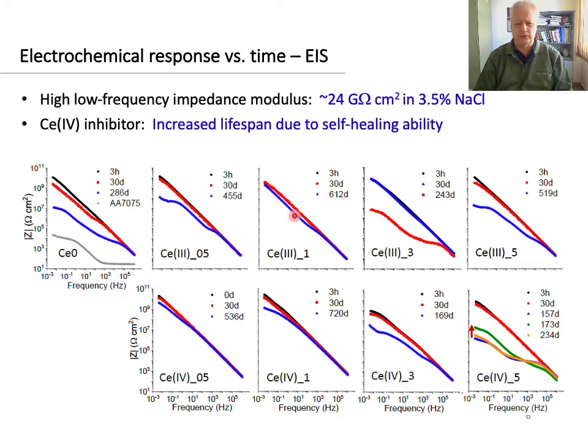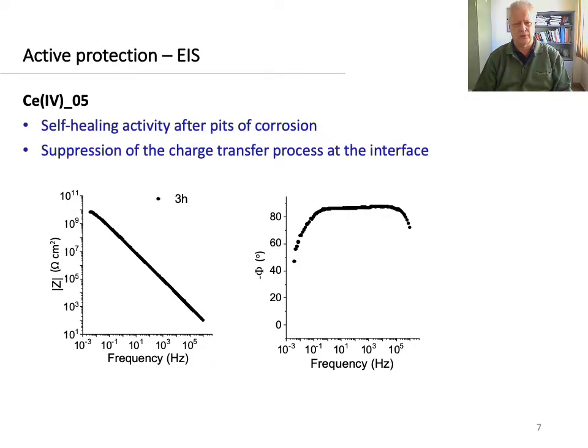Coatings with intermediate cerium-4 concentrations also provided excellent adhesion and corrosion protection with an impedance modulus higher than 4 gigaohm after more than 720 days of immersion observed for the cerium-4 1 coatings. This performance is related to the homogeneous cross-linked hybrid structure and the strong adhesion to the aluminum substrate. Although both coatings provided long-term protection, the self-healing ability as a key feature was observed only for the cerium-4 coatings. This can be seen here. The cerium-4 05 coating showed an impedance recovery after pitting.